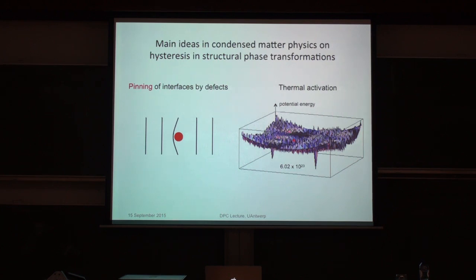So in any case, there's some average position, and now you cool the material. You take heat out of the material, so you decrease the thermal motion, and it has to find its way into one of those deep wells. Well, as you can imagine from the picture, it could be a lot harder to find one of those deep wells than it is to find your way out of one of those deep wells, and therefore the temperatures at which these occur could be different, and that's hysteresis. So that's the thermally activated idea of hysteresis, and as I said, these are not completely separate.